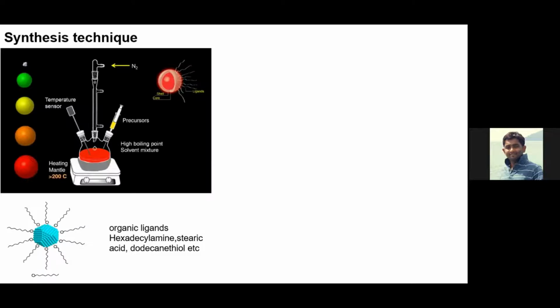Basically, as I told you earlier, these are very tiny crystals, and in synthesis we use some ligands. Ligands means some amines or thiols or different acids, not hydrochloric acid, but fatty acids like stearic acid, oleic acid. So you have a polar group here, and a very long tail of carbon chain. So these nanocrystals are generally dispersed in non-polar solvents like hexane, toluene, chloroform. Of course, you can also transfer them to water or polar solvent by changing the ligand, and people already use this for biological applications.